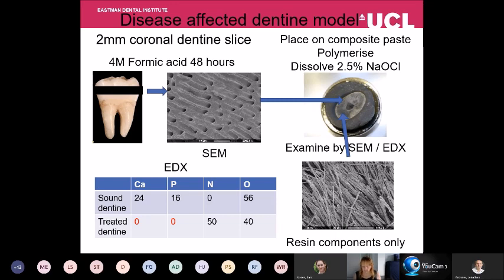In order to look at how different components affect the sealing ability, what we've done is we've had to make a disease-affected dentine model. To do this, we've taken 2 millimeter thick coronal dentine slices, and we've combined them with formic acid solutions, 4 molar formic acid for 48 hours. What that does is it dissolves away all the calcium and all the phosphate, all the mineral, but it leaves the collagen structure and the collagen tubules intact.